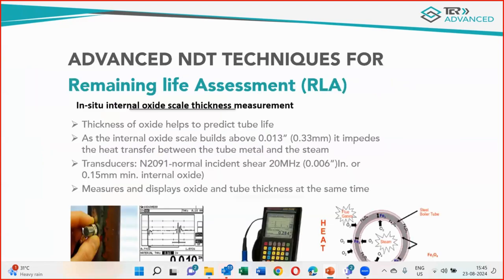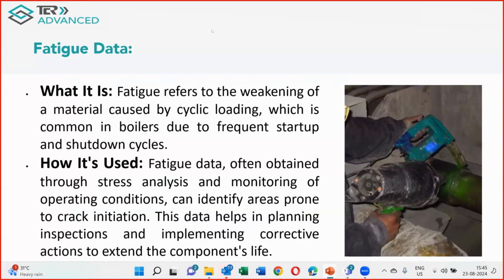So it can affect. Now, the other technique is the oxide scale thickness measurement, where it is possible to non-destructively measure the oxides in the boiler tubes. When you measure the oxide scale, the limitation of this technique is that it cannot detect less than 100 micron, maybe 120 micron and less. But most of the time I have seen that the scale thicknesses are much higher than 120, and this is an extremely useful tool which we deploy in the RLA. And we have 6 such equipment. So, we supply it for a lot of services.